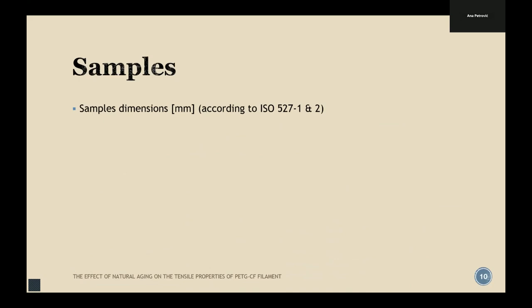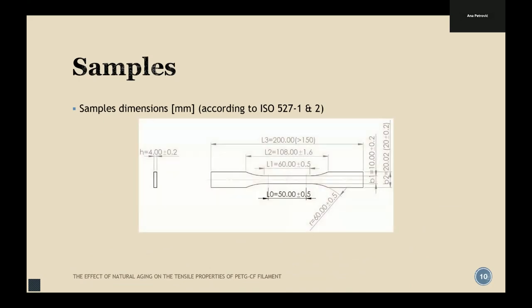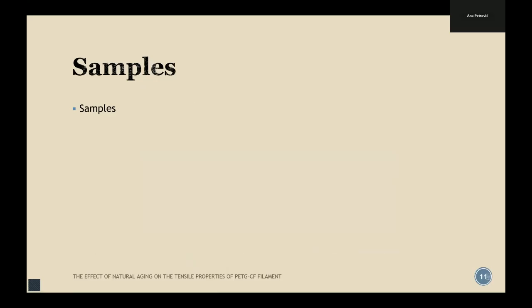The sample dimensions we chose are according to ISO 527-1 and 2. These are the dimensions according to the standards, in millimeters. We can see that the gauge length is 50 millimeters, so we will use that in the primary test. 6 samples are naturally aged for a period of 300 days in room conditions, as we also said, which does no harm.